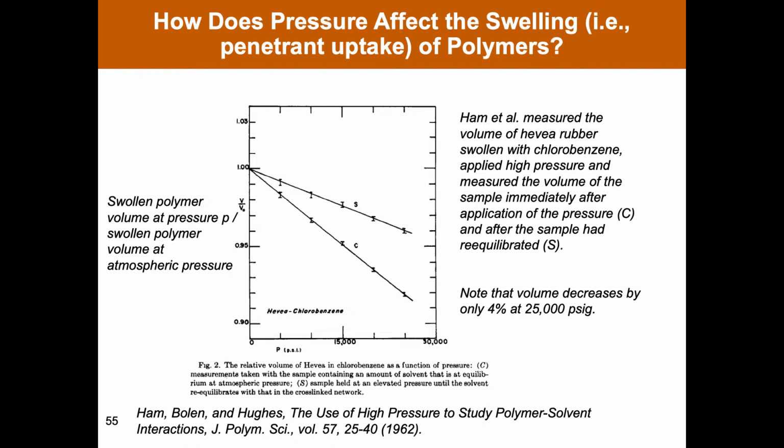And what they find is that immediately after applying pressure, they do see the volume of the sample decrease. And then gradually, if they hold the sample at pressure, the volume goes up again. So what's happening here? You compress the sample a little bit, and it gradually absorbs solvent back until it comes to equilibrium.